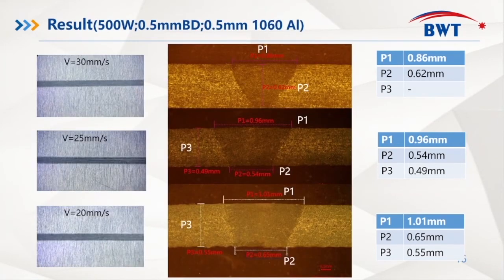Changing the metal to aluminum plate with 0.5 mm thickness, we use 500 watts power and the speed of 30 mm per second cannot penetrate. When the speed is 20 mm per second, the width of the weld bead on the top surface is 1.01 mm. The bottom width of the weld bead is 0.65 mm.